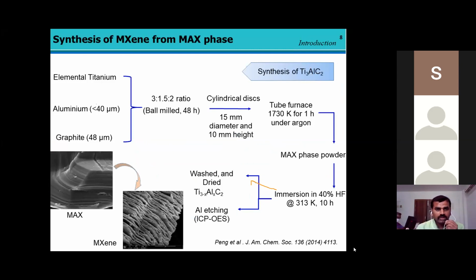How was the MXene material synthesized from MAX phase? Initially, they started with many methods, but this method is mostly adopted for the synthesis of titanium-based MAX phase. They started with a 3:1:2 ratio of elemental titanium, aluminum, and graphite-based material, which was ball milled for 48 hours. Then the powder form of this ball milled material was applied to the pressure instrument to make a cylindrical disc with a size of 15 millimeter diameter and 10 millimeter height. Then this disc was further treated in a tube furnace at about 1730 Kelvin for 1 hour under argon atmosphere. So the obtained MAX powder was titanium aluminum carbide, and this is the raw material for MXene.